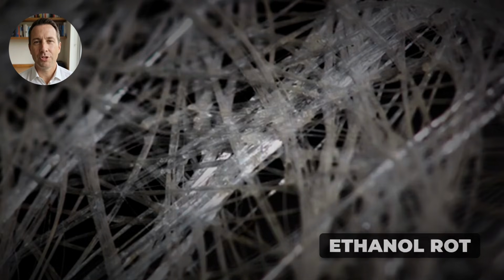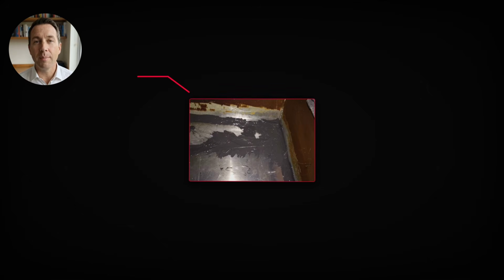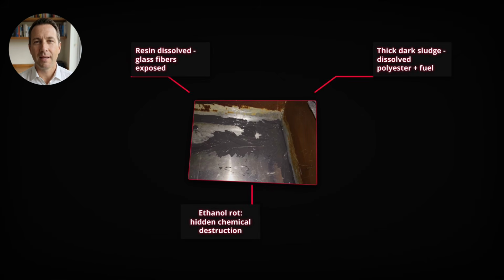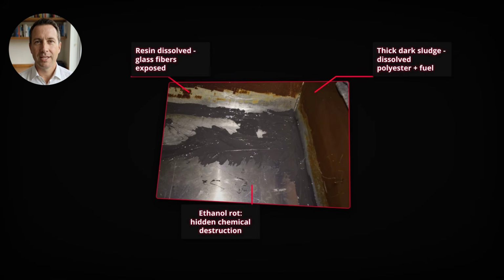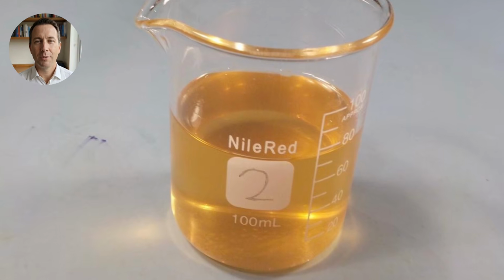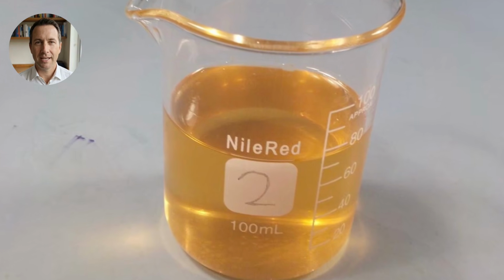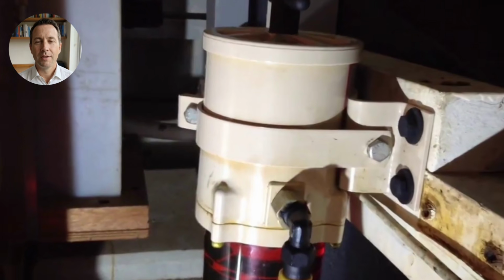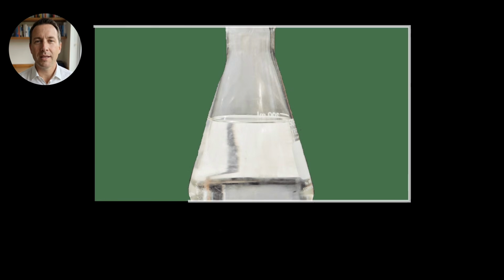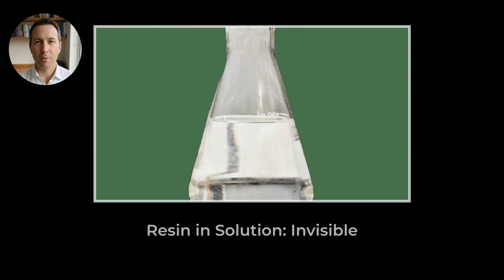White glass fibers exposed where resin used to be. A thick layer of dark brown to black sludge pooled at the bottom. A mix of dissolved polyester resin and fuel residue that smells like a chemical plant. And here is the part that makes this especially nasty. Those dissolved resin compounds pass straight through your fuel filter because they are in solution, not in particle form.